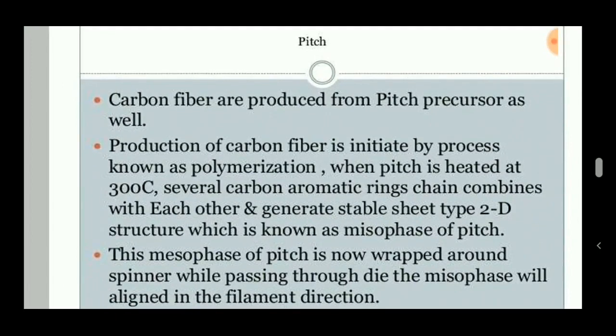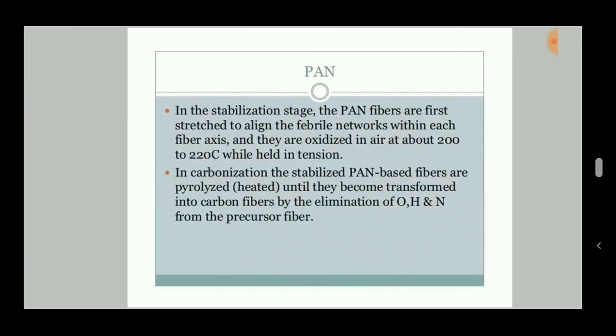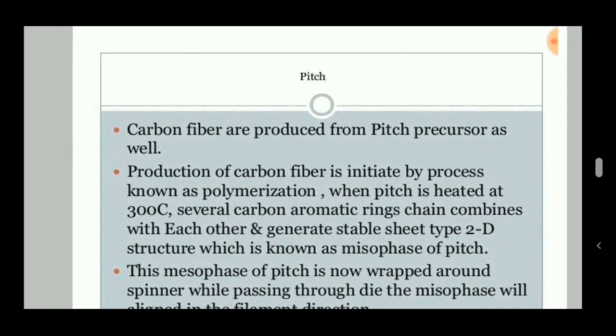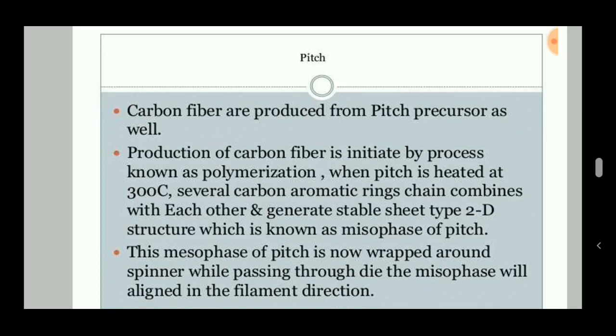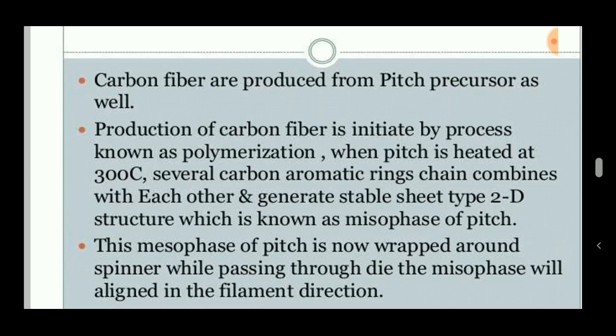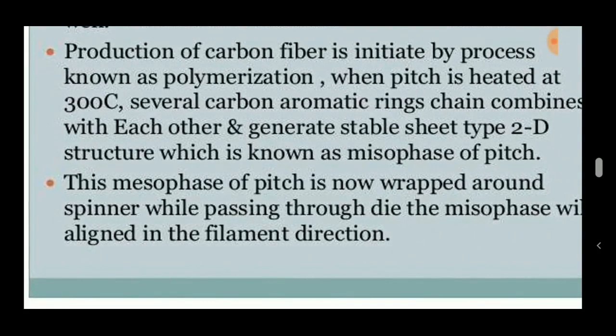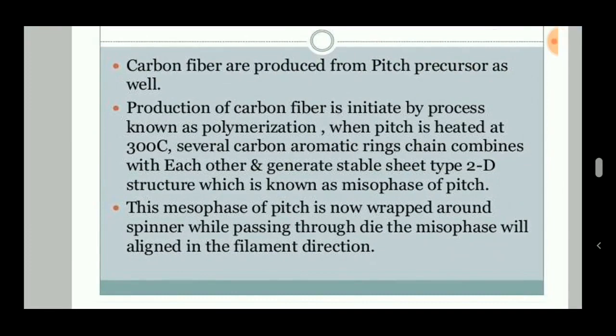Carbon fibers can also be produced from a pitch precursor. We have seen how carbon fibers are made from the PAN component; now we look at how they are made from pitch. The pitch is heated at 300 degrees Celsius, and several carbon aromatic ring chains combine with each other to generate a stable sheet-type 2D structure known as the mesophase of pitch. While passing through the die, the mesophase aligns in the filament direction.